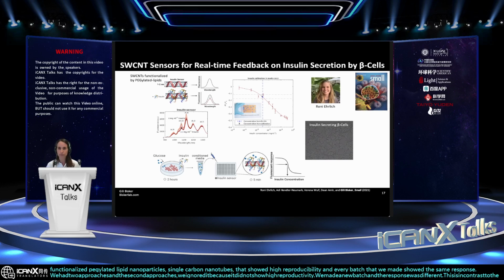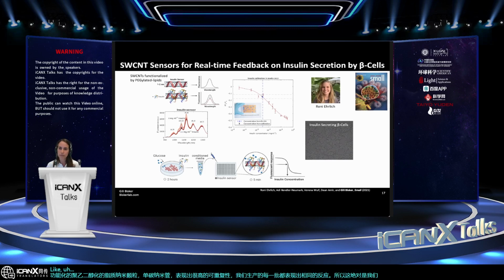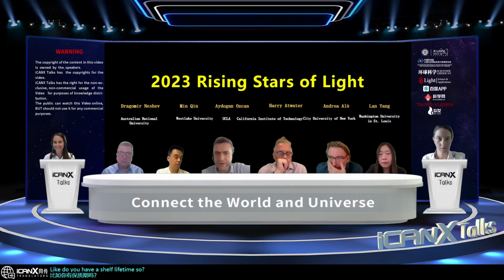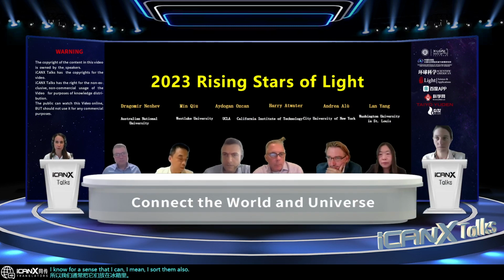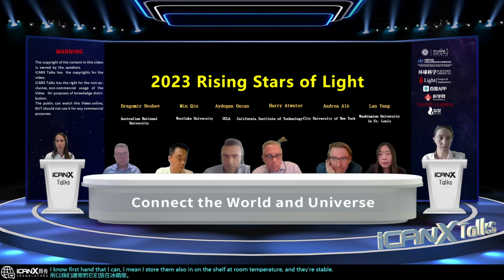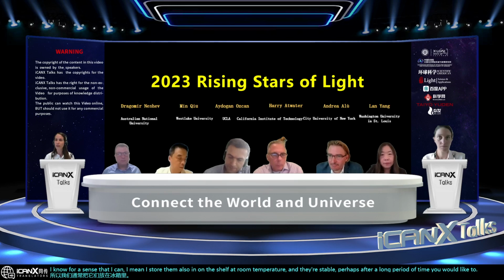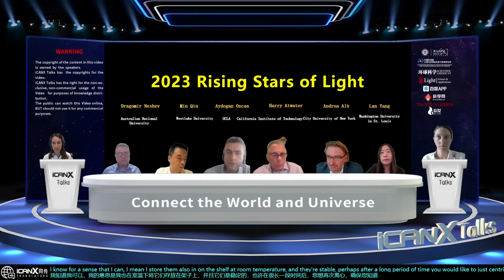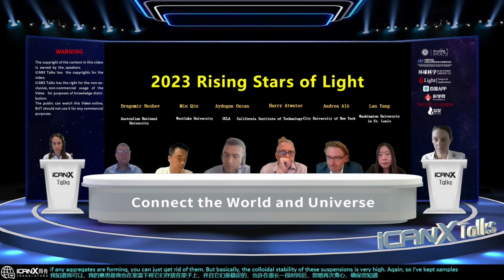How do you store these sensors? Do you have a shelf lifetime? Do you have any degradation? We store them usually in the fridge, but I know firsthand that I store them also on the shelf at room temperature, and they're stable. Perhaps after a long period of time, you would want to centrifuge again, to get rid of any aggregates that may be forming. But basically, the colloidal stability of these suspensions is very high. I've kept samples for more than a year on the shelf. Thank you.